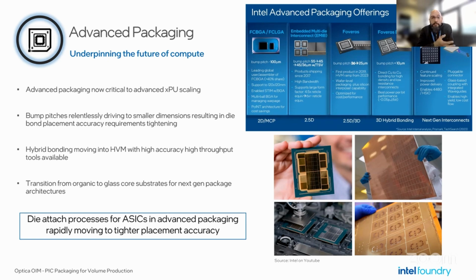Following that, bonding technology is rapidly advancing. For example, hybrid bonding is now moving into high volume production. There are tools available on the market that can achieve very high levels of placement accuracy from die to wafer, like deep sub-micron. In addition to that, we're seeing a long-term trend to transition the core substrate material from organic to glass core substrates, as has been mentioned before. This is aimed at providing enhanced performance and better thermomechanical stability in the longer term.